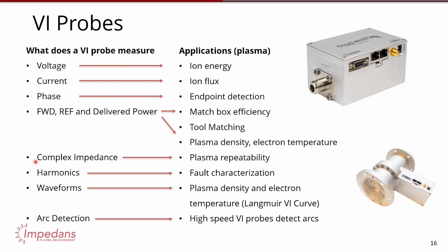I forgot to mention that here. You measure the complex impedance of the load. You can measure harmonics, and obviously you still have the original waveforms available. Each of these enables pretty powerful applications if you use them intelligently, and I'll show examples of this later on in the slides. So, for example, using just the voltage measured on a VI probe, you can get information about the ion energies inside, processing a wafer.